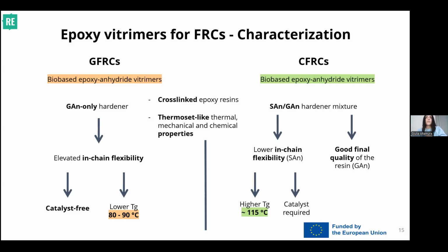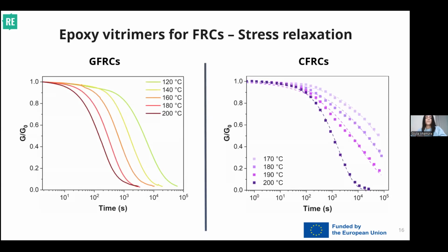Now that we have characterized our resin, we want to know if it's a vitrimer or not. So, as I said before, we need to do some stress relaxation experiment. As I mentioned before, if it relaxes, it's a vitrimer. So if the modulus decreases over time, and they do, it's a vitrimer. So we can say that these formulations are both vitrimers. And we can also observe that relaxation is faster as we increase the temperature, of course, due to kinetic reasons.